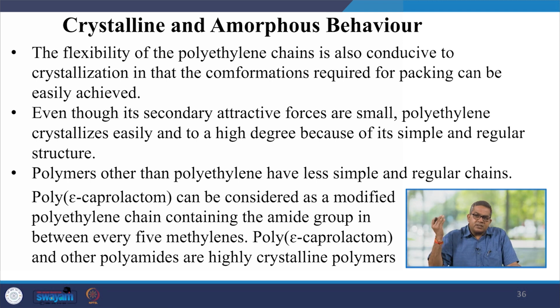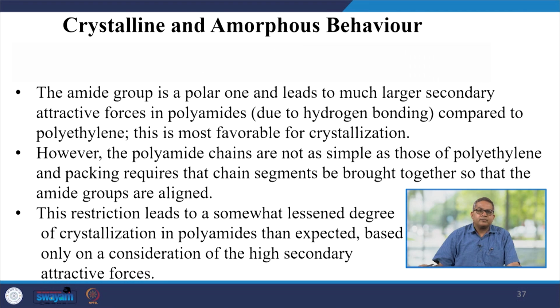Polycaprolactam can be considered a modified polyethylene, in which the chain contains an amide group between every 5 methylene groups. Polycaprolactam and other polyamides are highly crystalline polymers, since the amide group is a polar one and leads to a much larger secondary attractive force in polyamide. This is due to hydrogen bonding.